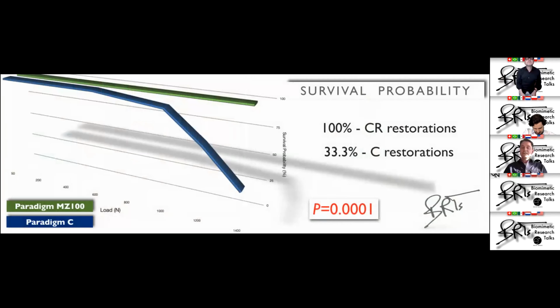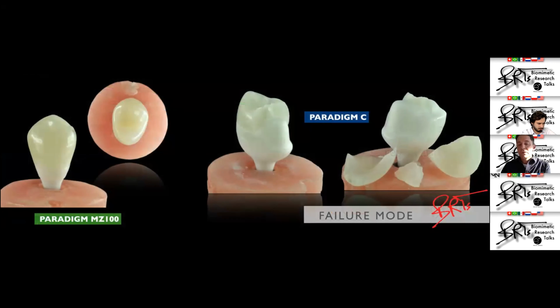As a result, we can see the outstanding performance of composite resin with no failure, while of the ceramic restorations, only 33% survived the fatigue tests. It's important to say that up to 600 newtons, all samples survived, and composite resin, as a resilient material, appears to make the difference at high loads, especially over 1,000 newtons. When we analyze the failure mode, there was no failure in the composite resin; all survived. In the ceramic ones, there is partial or total failure, as you can see in the pictures, with no abutment fracture and no screw loosening in the test.